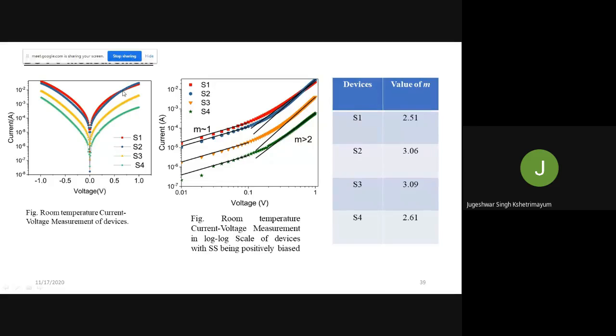The IV curve generally follows V to the power m. Here m is almost equal to 1. Here m is more than 2. So m equals 1, this follows from 0 up to 0.1. We can say the device is following the Ohmic conduction mechanism. But as we increase the potential, we found that it is no longer ohmic; it is coming from the trap-controlled conduction mechanism, because m is more than 2. If m is 2, then it is more Child's law, which we know.